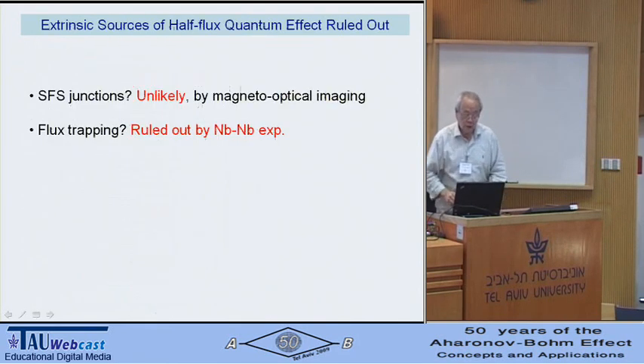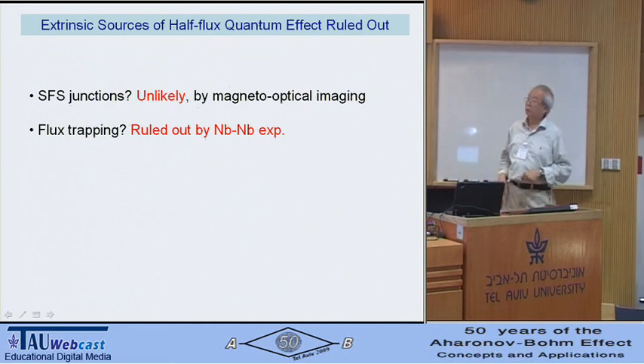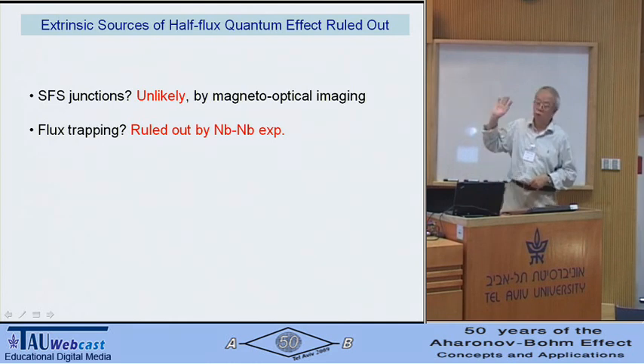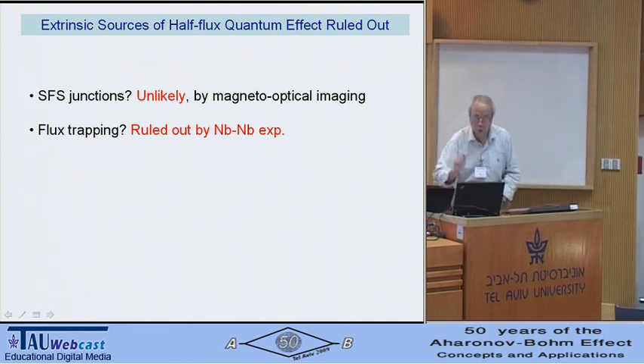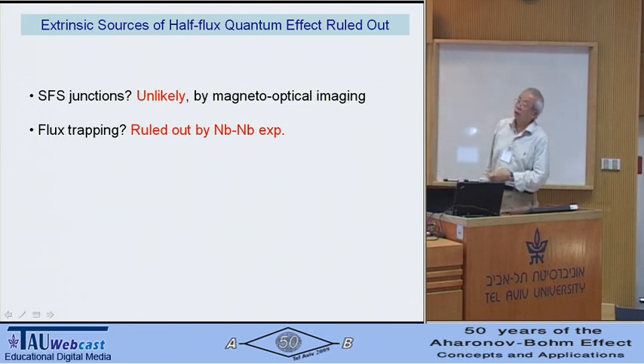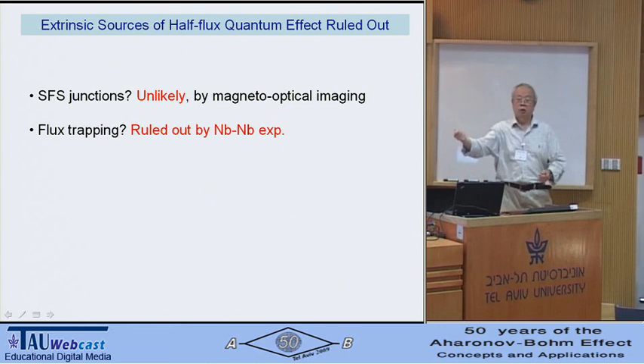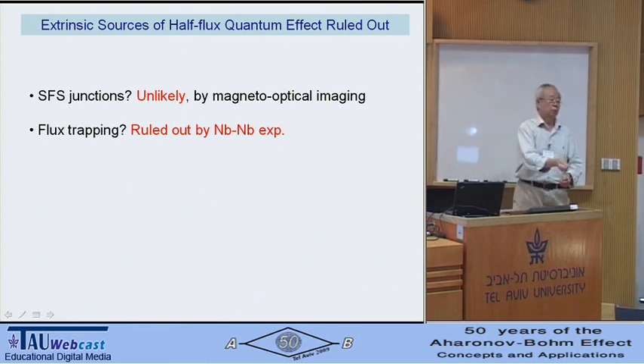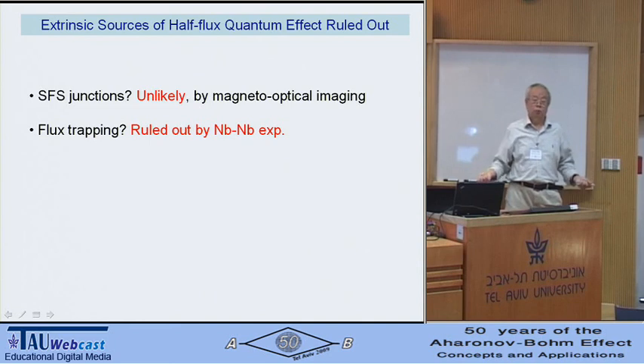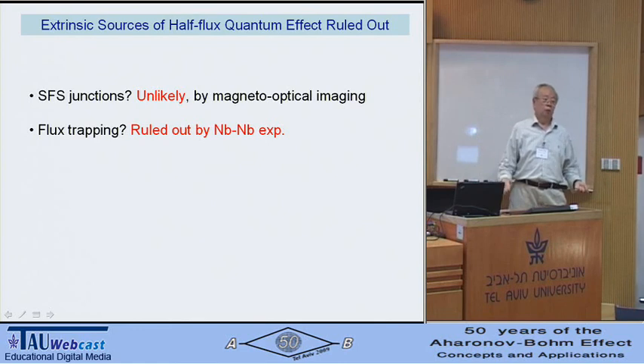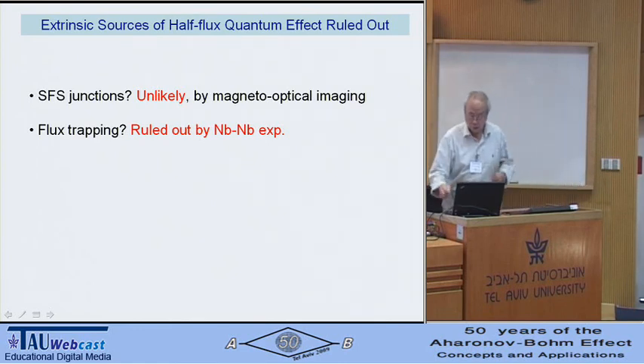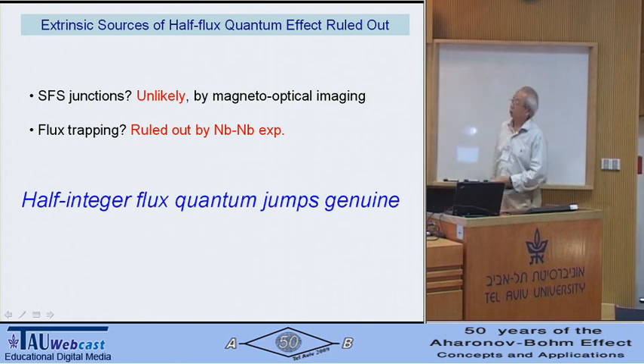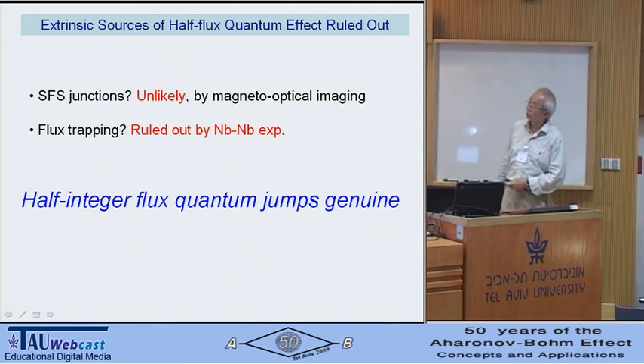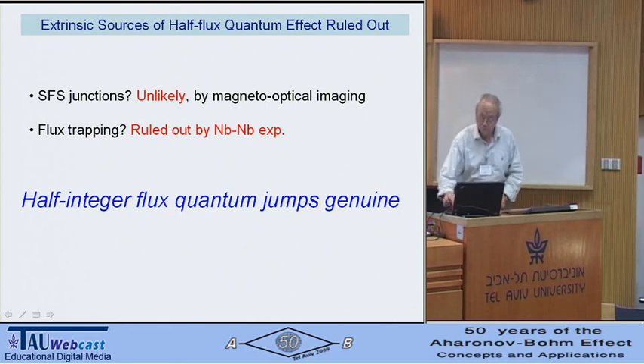Okay. Now people will start worrying, especially my postdoc, about whether this could be an artifact. Could it be something else? So we try to rule out all the other possibilities. I don't have time to go through them. Oh, yeah, one thing I want to mention, this experiment setup is very nice. You could just pull out the polycrystalline material, put niobium back in, and nothing weird will happen. You should see single flux. We never saw any half flux. So that's very reassuring. The thing we saw was really genuine. So the half flux quantum jump really is not an artifact.